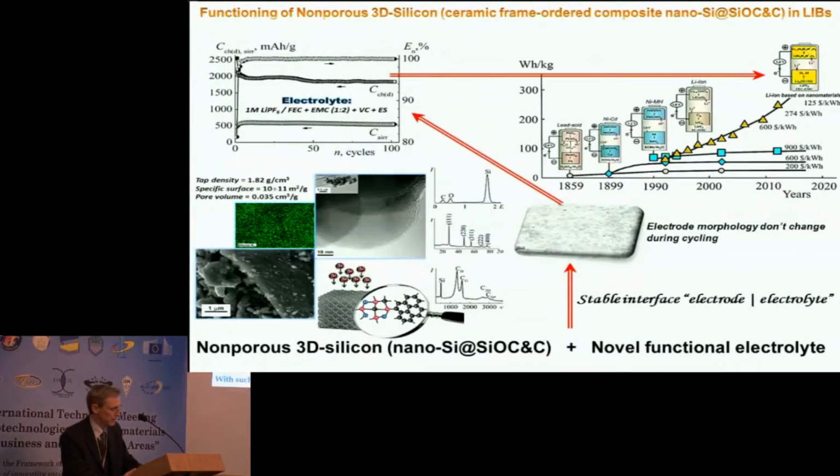For example, readily available and cheap silicon is able to store 3.75 lithium atoms per atom of silicon in the form of the following composition: Li15Si4. The higher amount of lithium that can be reversibly stored leads to a significantly increased theoretical gravimetric capacity of silicon with 3,579 mAh per gram, compared to 372 mAh per gram for graphite, which is able to store 1 lithium atom per 6 atoms of carbon.